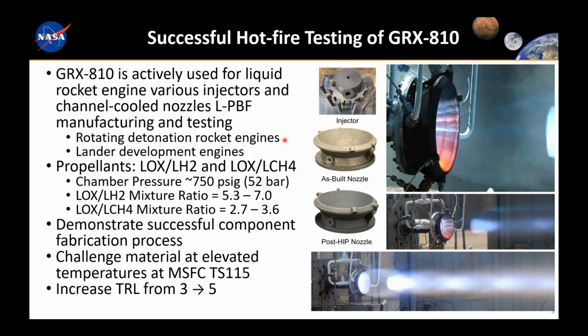To date, we have tested several nozzles and injectors that I'll show a little bit later. But I think one of the things that I wanted to point out here are some of the propellants that we're using, both liquid oxygen, liquid hydrogen, and liquid oxygen and liquid methane propellants. You can see an example here of the liquid hydrogen in the upper right and the liquid methane in the bottom right. And we see compatibility with these propellants, and particularly some of the chamber pressures that we've run at, up to about 52 bar in the various mixture ratios.